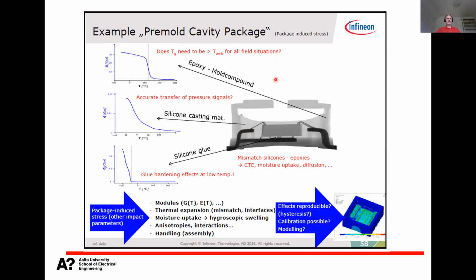Then, in order to allow the pressure to enter the actual MEMS, you need to have something which seals the membrane from dust and particles and humidity and everything, but still allows the pressure to be sensed. So typically you have this kind of very soft silicone gel here protecting the actual membrane. And in fact, this silicone gel does not have any exact glass transition temperature. It changes its mechanical properties like this. So it is getting softer and softer when the temperature goes up, but you don't have any, let's say, direct line here. So you would need to have, let's say, a polynomial to describe it.